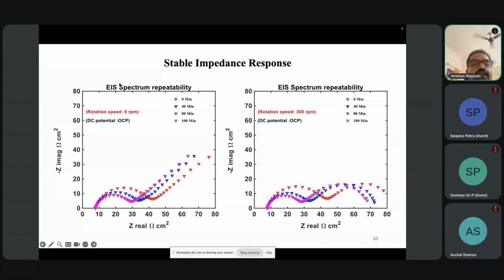So what we have done is we have done the impedance at different intervals of time. Whenever we got the stable impedance, you see at 80 minutes and 100 minutes, there is no change. Only then we can go for the impedance measurement. I have often seen in literature people make a lithium-ion battery. As soon as they make it, they measure impedance. After a few cycles, they measure impedance again, and then they claim there is a decrease in impedance. True, there is a decrease in impedance, but there is nothing surprising in that. Therefore, you should allow the system to equilibrate first and then do this measurement.